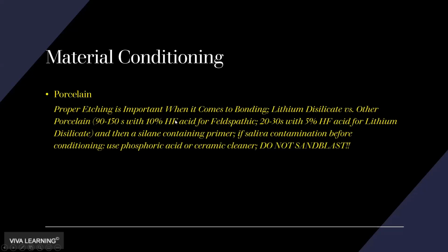And of course, there are ceramic primers out there on the market if you don't like to use the hydrofluoric acid. And of course, you have to use less time and a lower concentration with lithium disilicate in order to get an ideal etch of the material. And of course, we do not, I repeat, do not sandblast the inside, especially lithium disilicates, because it can create microfractures. And of course, that can lead to long-term restoration failure.